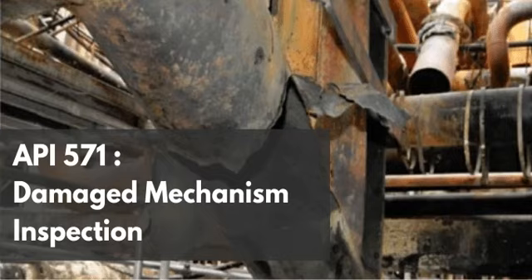Yeah, and if you remove even a single element from that equation, the entire mechanism just arrests. It stops completely. The requirement for a free liquid water phase is absolute. We aren't talking about high humidity or steam vapor here. Right, it can't just be a gas. No, there must be a physical condensing liquid water film in direct contact with the steel, because that liquid water acts as the electrolyte. Without the electrolyte, the specific localized anodic dissolution required for the cracks to propagate simply cannot occur. Period.